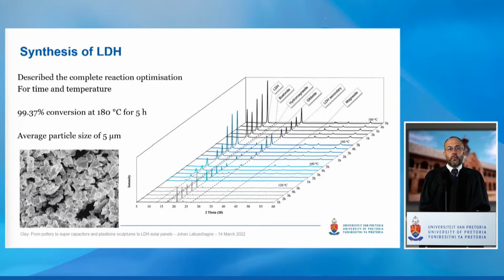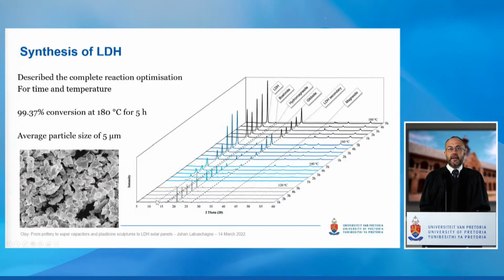In this synthesis, we actually try to optimize the temperature and time of the reaction. You can see on this graph many XRD graphs stacked together and grouped by temperature from 120 to 180 degrees Celsius, and in time from 1 to 5 hours. The first peak on the diagram, this one here in all of them, is the peak that indicates the LDH. And you can see increasing temperature, and in a temperature range, increasing the time typically leads to a better yield.